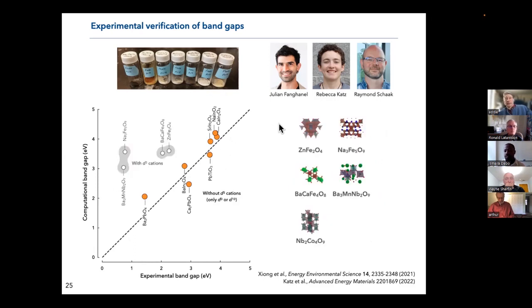But we also have material, if we go further into the analysis, that are not on that trend. And further analysis enables us then to understand the origin of this discrepancy. If you look closely, many of those materials involve manganese, iron, cobalt, so essentially magnetic elements, so elements that are susceptible to develop magnetism. And whenever you have magnetism, you need to go beyond the method that we use here in order to be more specific in the description of magnetic order and the arrangement of the spin of the electrons across the material. So this typically happens for transition metals.